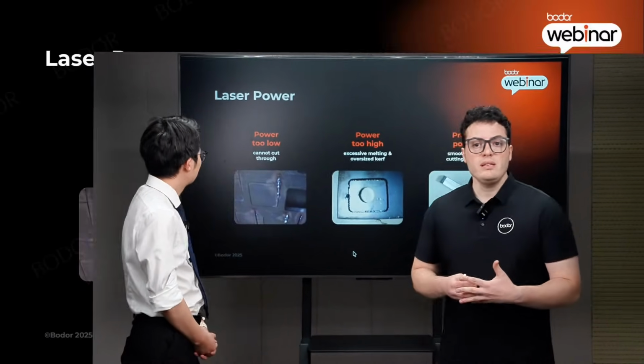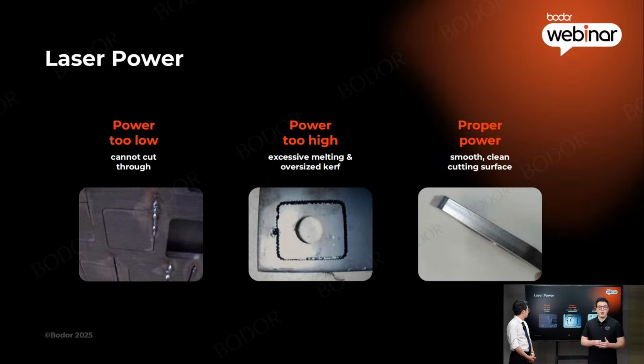On the left, you can see what happens when the power is too low. The beam does not fully penetrate, and you end up with an incomplete cut. In the middle image, the power is too high. The metal overheats, the kerf becomes wider, and the edge turns rough and over-melted.